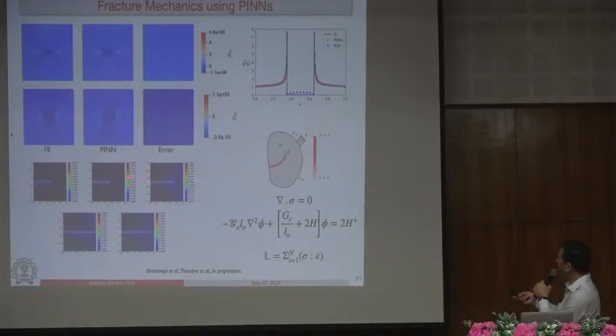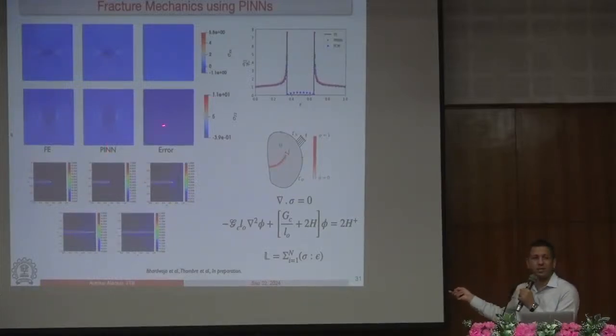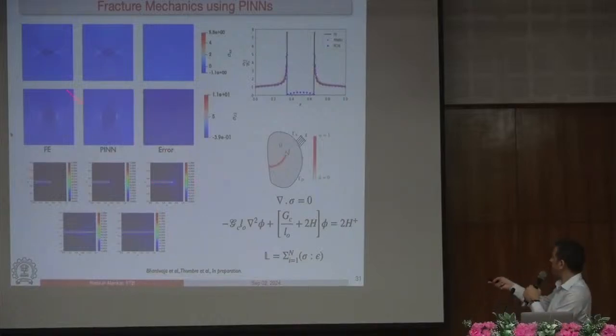Right? We have now recently also captured phase field fracture mechanics using PINNs. We are able to simulate what is the stress concentration at the tip. We have also coupled it with crack propagation in phase field. So in phase field fracture mechanics, what we do is we solve the momentum balance. We solve this phase field equation for crack propagation, right? And then we have this loss function, which is nothing but the amount of energy.